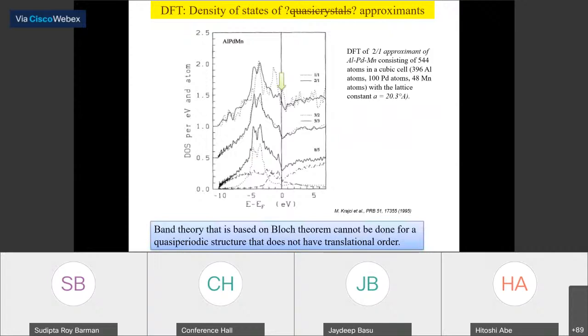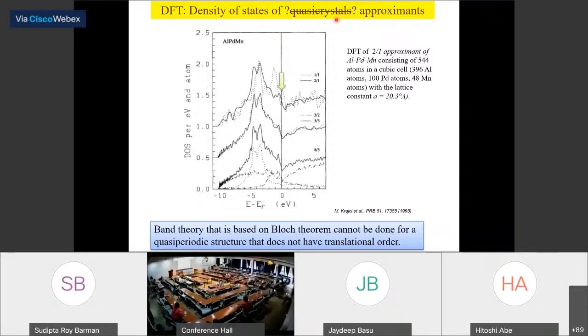So you see here, there were quasicrystals here because everybody does DFT of approximants and imagines that these are actually quasicrystals. So these are all approximants. And you can see that the size of the approximants is increasing. This is a work by Marian Krajci from long back. And as the size of the approximant is increasing, the depth of the pseudo gap is increasing. And this is the Fermi level. And so the approximants themselves also show a pseudo gap.